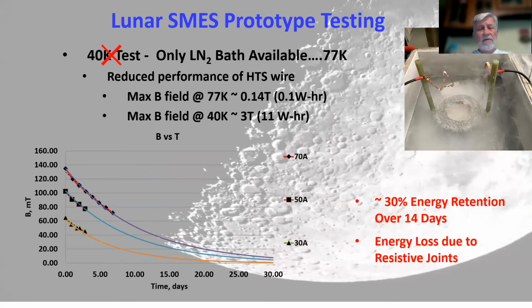As I noted, the test was to be at 40 degrees Kelvin. The cryocooler and vacuum chamber were not available for that, so we decided to test only in liquid nitrogen at 77 degrees Kelvin. That reduces the performance of the wire. So our maximum field was only about a tenth of a Tesla versus the 3 Tesla we projected at 40 degrees Kelvin. So we had only a small amount of energy that was stored.